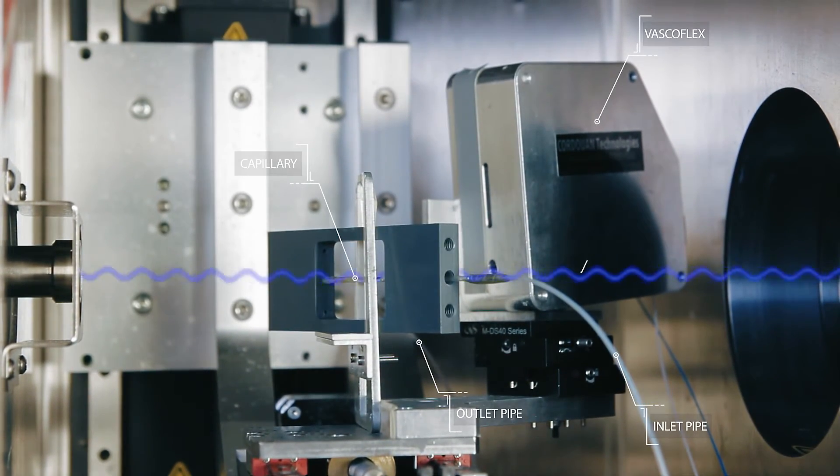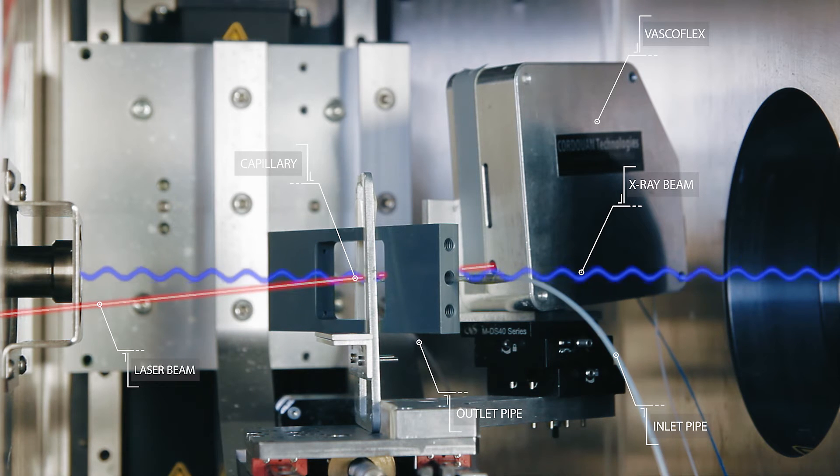In the next stage, the suspension of nanoparticles runs through a flow-through capillary. An X-ray and a laser beam hit the capillary at the same time and position, enabling simultaneous measurement of the nanoparticle size by small angle X-ray scattering and of the hydrodynamic diameter by means of dynamic light scattering.